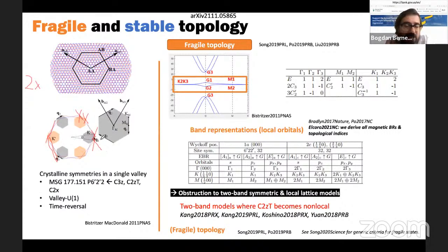And if I didn't have any coupling between the layers, that would be the physics. Now I have coupling between the layers, and it turns out that the coupling between the layers obviously is much smaller than the in-plane coupling. So now let's understand the physics. If I take these 2 Dirac fermions, I form a new Brillouin zone, which is given by the difference in the wave vector between the rotated K points of the lower and upper layer. And if this is the Dirac momentum of the large graphene Brillouin zone, then this Q is K_D times theta, roughly. And this small gray Brillouin zone is the Brillouin zone of the moire lattice, of the new large periodicity lattice. And I form another Brillouin zone around the K prime point.